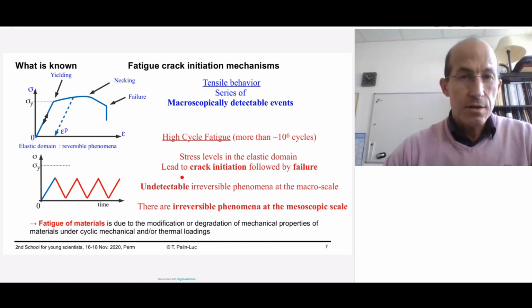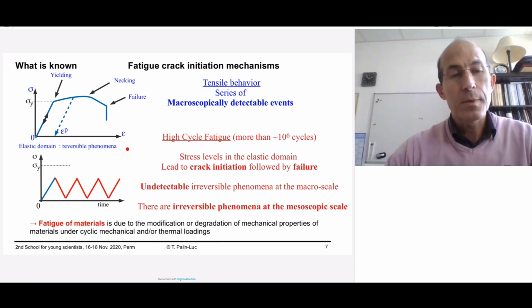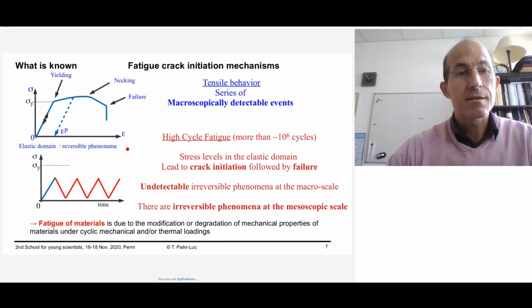The fatigue crack initiation phenomenon is characterized by typical features. That is, if you compare the stress level during a monotonic quasi-static tensile test with the fatigue phenomena, you cannot see anything in fatigue. I mean that during a macroscopic tensile monotonic quasi-static test, many macroscopic events like the plastic flow, when the stress is above the yield strength, then necking, and then failure are characteristic. And if you load the material after the yielding, there are macroscopic plastic strains.